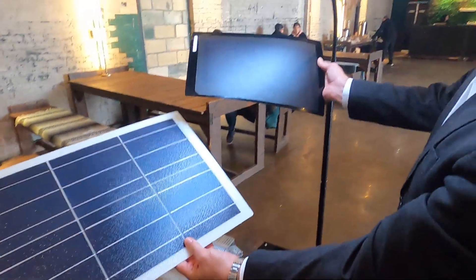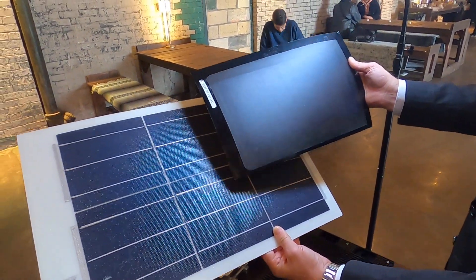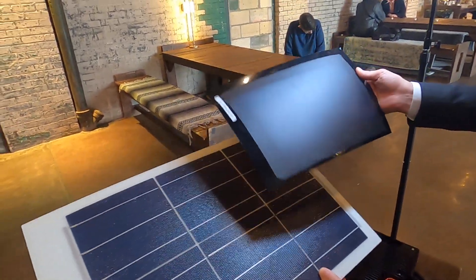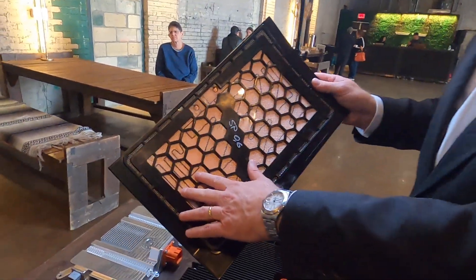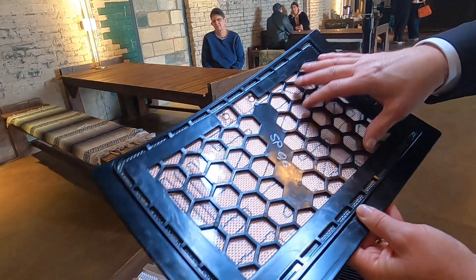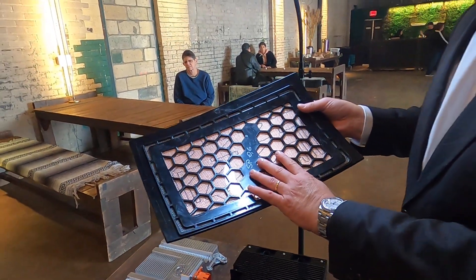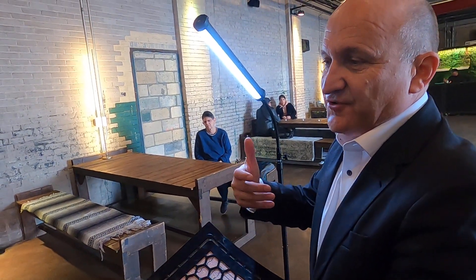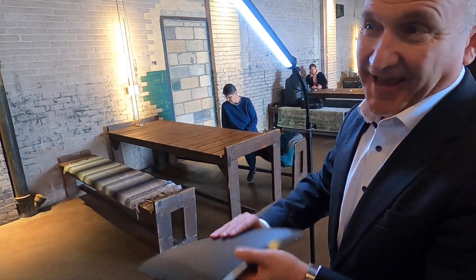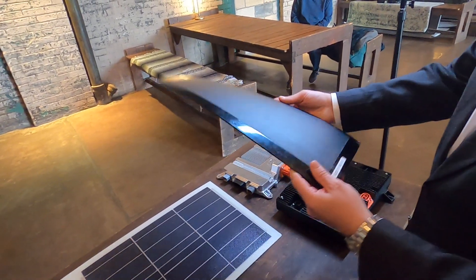What we've done here versus here: first, we decided that all these silver stripes you know from regular solar panels are basically taking the power from the solar wafer and transporting it to whatever receiver you want to consume the power. In our case, we chose copper back-contacted solar cells. Here we have copper back contact for four solar cells, and here you can see the two areas where you can take the power off. But the proof of the technology is not our choice of the solar wafers, which we do not produce. Our capability is to integrate the very brittle solar wafers into an injection molding process with very high pressure injection polymer and have the solar wafers not break when you inject it and not break in the next 10 to 20 years when you drive your car.